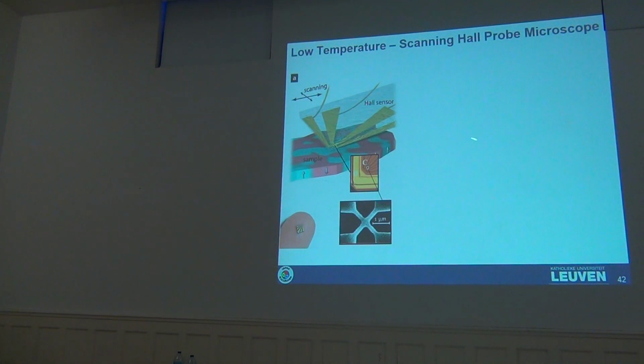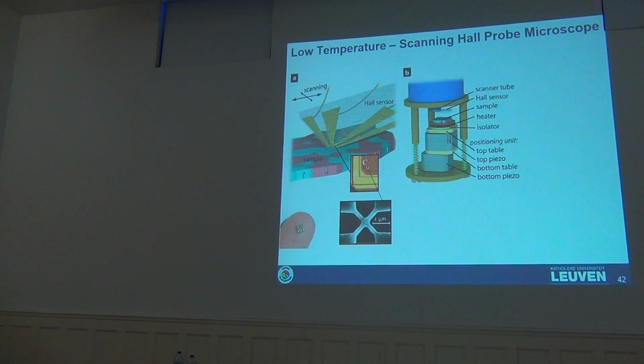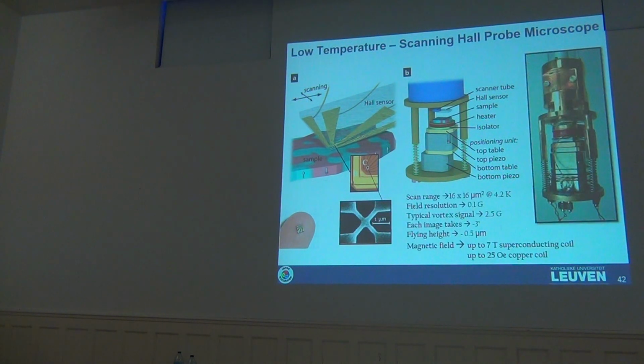And then you use a powerful technique like any scanning probe, also discussed a lot yesterday, and you can scan and measure local magnetic fields quite nicely, and you can have a precise map of local magnetic fields at the top of a superconducting material. Then you put it in a superconducting solenoid, and normally you put there 2 samples. One is a typical type 2 superconductor, just to calibrate your system, and next to it you put the sample you want to investigate.